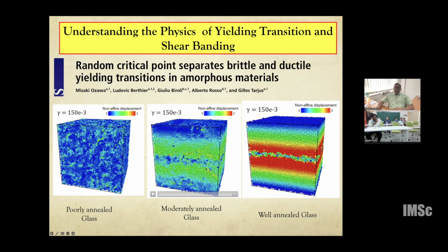And you see that the plasticity, which is color-coded using the non-affine displacement, which I'm not going into the details of, is very different. Particularly in a poorly annealed glass, you see that plasticity is happening everywhere, and it's kind of a homogeneous yielding process. In a moderately annealed glass, there is some signature of localization of plasticity. But in a well-annealed glass, you see a very, very clean localization of plasticity. And this is the shear band. So now, even on a computer, one can easily generate shear bands and actually study what leads to such shear band formations.